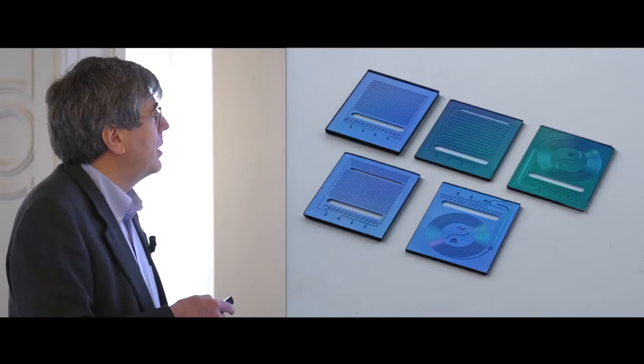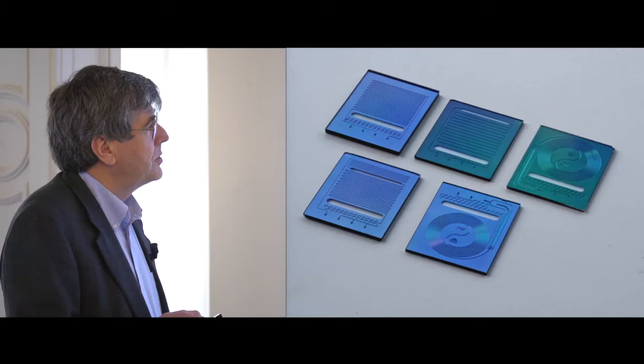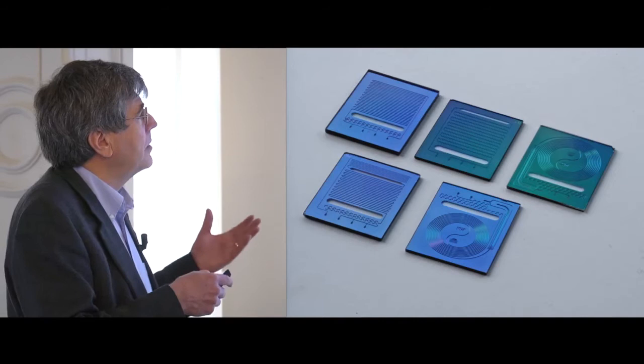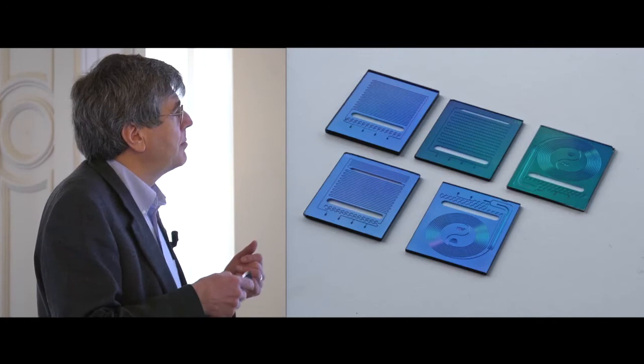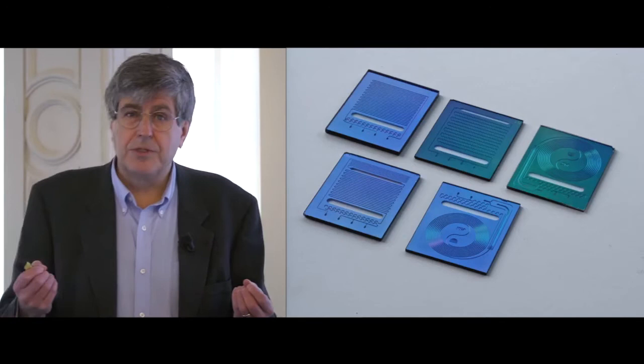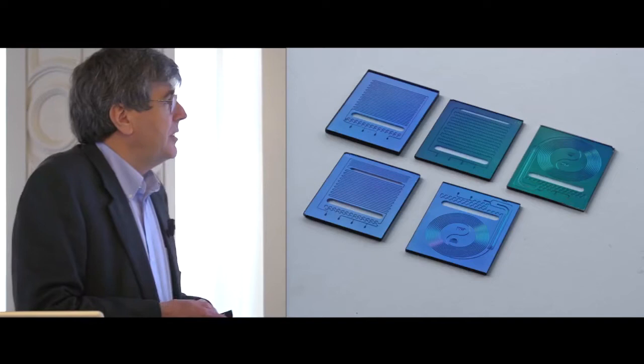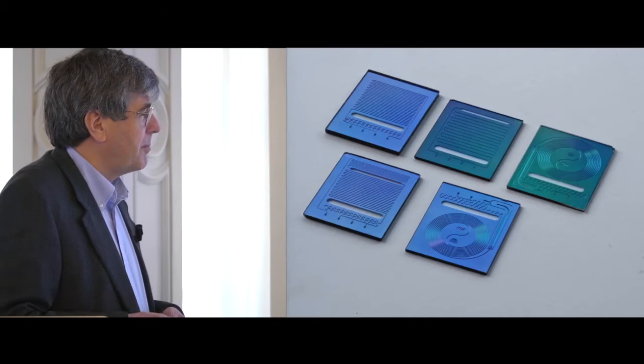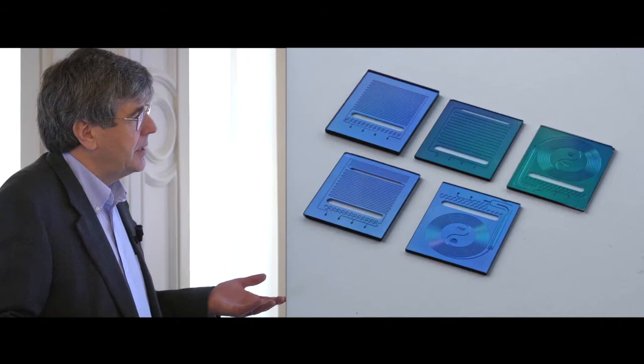These reactors have one common feature: an area where the silicon is missing, providing a thermal barrier — a poor thermal conductivity area. This can be kept at a temperature ramp or constant temperature, while the other end is kept cool. This means you can heat one part without heating the other, which is important for the sealing technology because otherwise thermal expansion coefficients will cause leaks or breakage of the chips. You can view them essentially as a tube that coils up and runs back again, with mixing elements and quenching elements integrated into the systems.